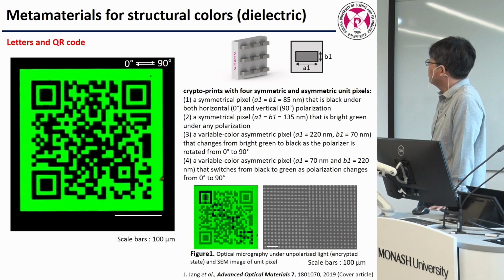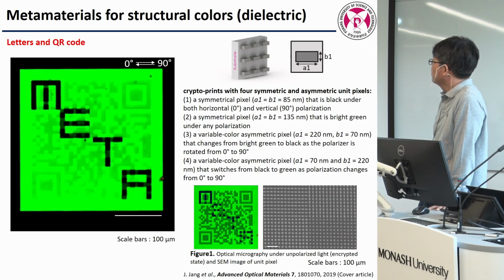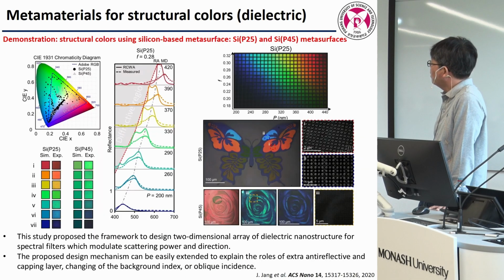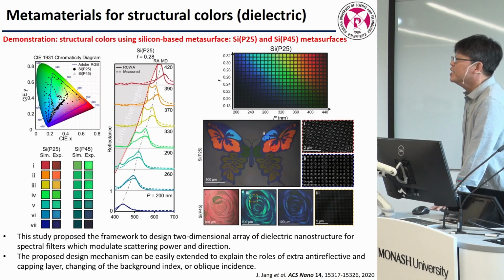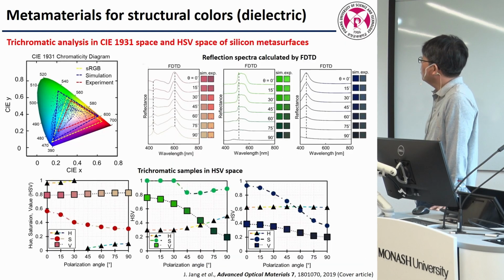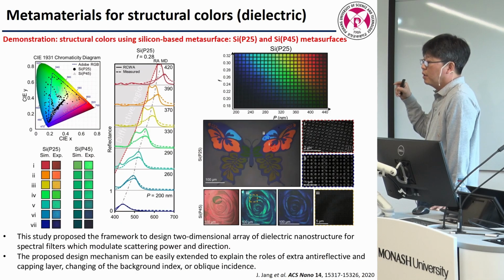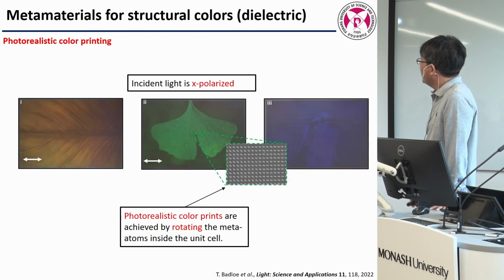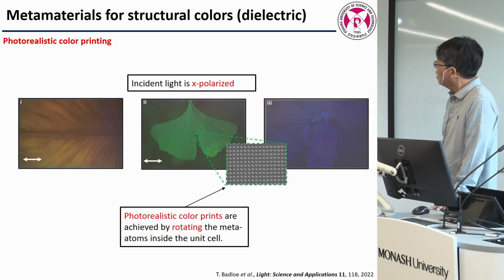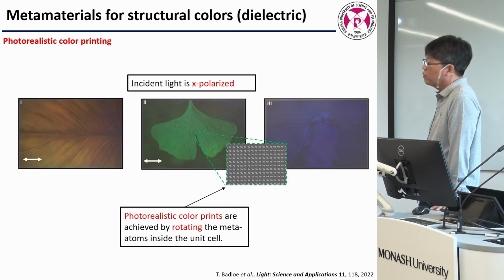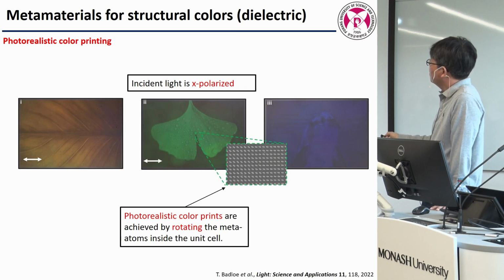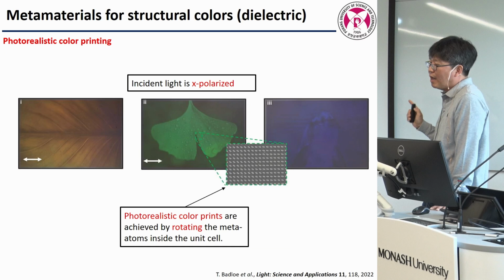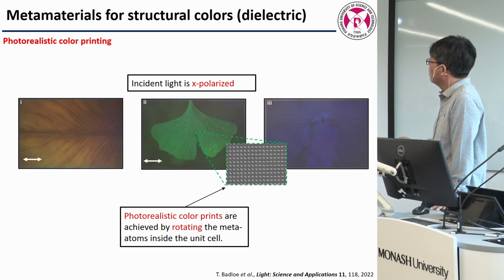And this is an earlier demonstration, simple green color only, a few humble images, and later it got better. We used engineered silicon. So this is normal silicon, but we added some hydrogen to suppress the k value. So this gets a little better color, but still not the best. And finally, we made a very high resolution, 100,000 dpi. So you can see almost photorealistic color. Humans cannot recognize this as silicon. It looks just like a photo. Anyway, 100,000 dpi is the maximum humans can recognize. So in terms of resolution, maybe it's enough now using this nanostructure.